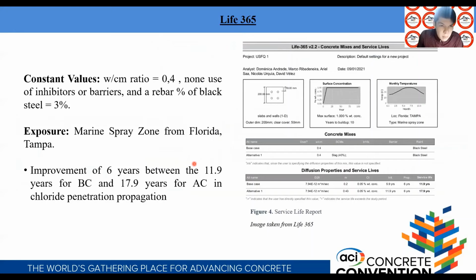Based on the mentioned properties, the Life-365 software calculated an improvement of 6 years, between the 11.9 years for the base case and 17.9 years for the alternative case, in chloride penetration propagation, a fact that increases the service life of the mixture against chloride exposure.